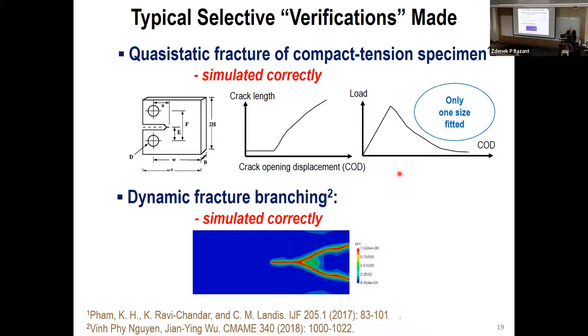If you go to computational journal papers, they typically use just these tests and nothing else. So the compact tension specimen is a basic specimen. You extend it and the crack grows. So you measure crack length, plot it against crack opening, and this is easily matched by the phase field model, also by dozens of other models. And the load-deflection curve can be measured, and that's also easily matched.